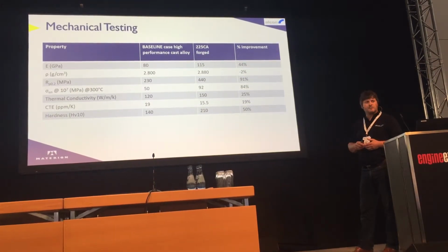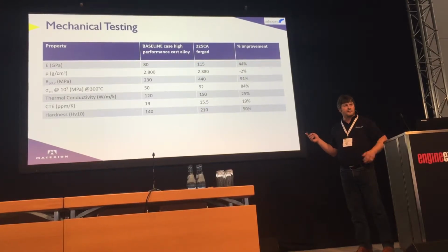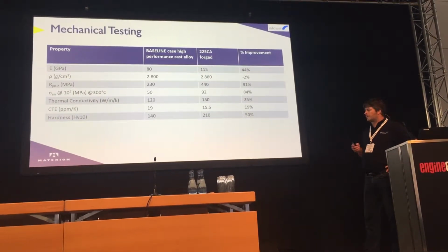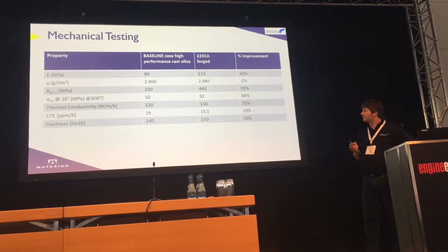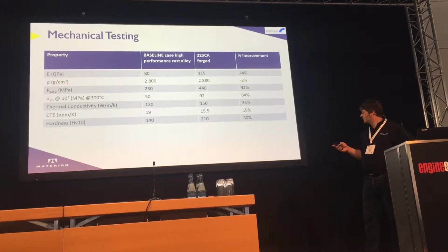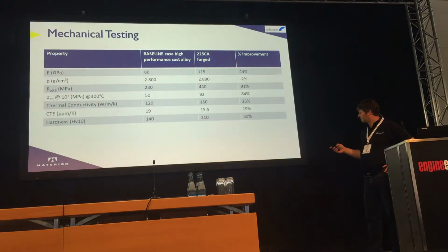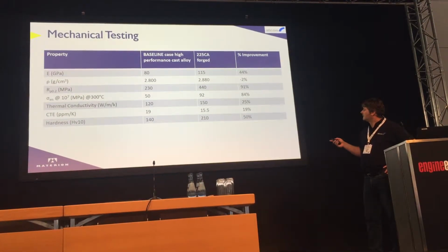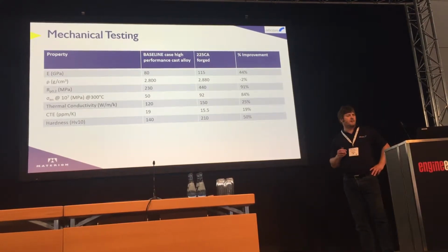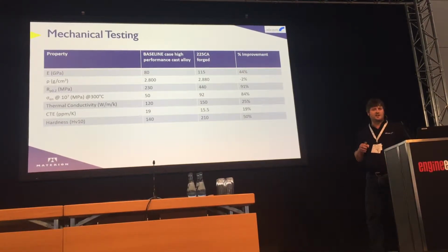The baseline alloy that is used by Jaguar Land Rover is a very high performance cast alloy. When you compare that alloy to the new material that we've developed, we achieved a 44% improvement in terms of the Young's modulus. Very similar in terms of density, proof stress nearly 100% more. But probably the most important one, and one of the reasons we look at using MMC for pistons, is its high temperature fatigue strength, which is significantly higher, 84% higher than the standard material.